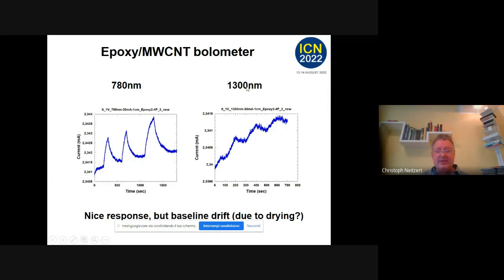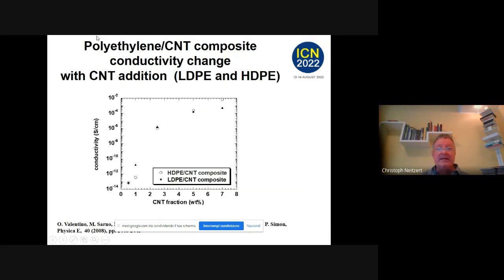And at 1300 nanometers here, we have something like accumulation. That means something is changing. And what we think is maybe with illumination that is penetrating into the sample, we change the humidity. If we change the humidity, we change the resistance. It's a very small change, if you see. But it's again the humidity sensor indirectly by the baseline. And you see it's not so good a bolometer. Okay, next one is polyethylene carbon nanotube composites.